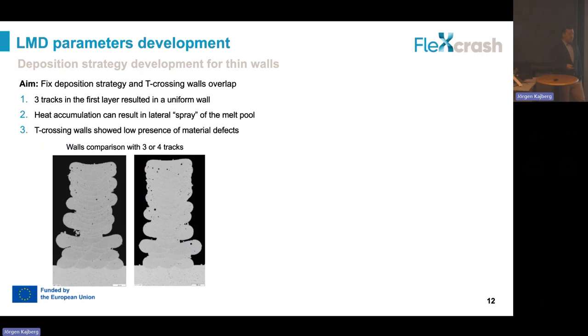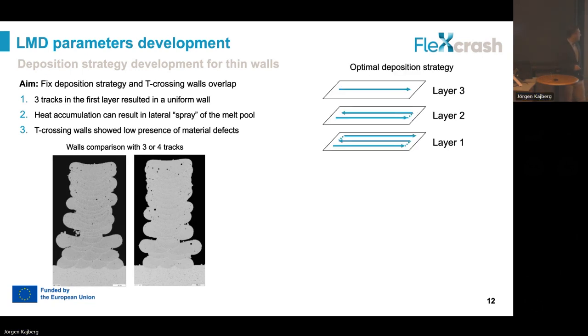So we went further to optimize this, trying to have this pyramid shape at the base of the wall that we deposit. And we found out that the best strategy is to have 3 tracks in the first layer, 2 in the second one, and 1 further on.